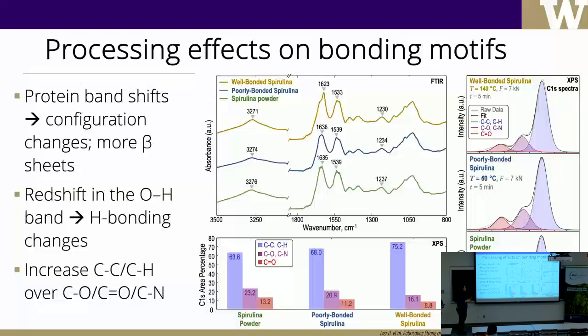So we can already see a couple of things. First, if we look at the protein area, and maybe the amide 1 peak over here, you can already see that your peak contour has changed, and you actually have almost two separate peaks, or a peak in the lower wave numbers indicative of more beta sheet formation. Then we do the convolution for the alpha helixes, beta sheets, and whatnot, and we can see that you do have a shift towards forming more beta sheets in the better pressed conditions, which you don't have here, though you do still have some difference between the poorly bonded and the powder. So we can say that something is changing in our protein. We can keep it at that level for the discussion right now.